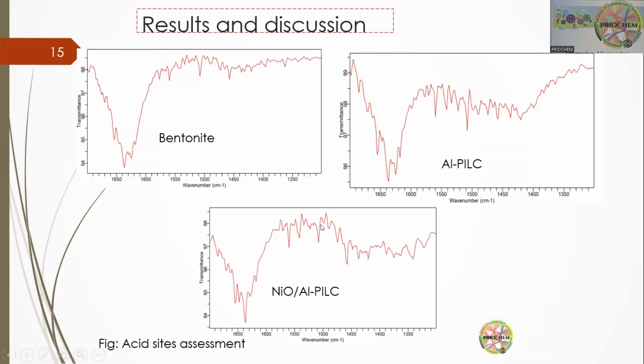Here is the pyridine adsorption in continuation with FTIR. The bands around 1440 and around 1595 correspond to the Lewis acidity, while the ones around 1500 correspond to the combination of Lewis acidity and Bronsted acidity. Here we did not quantify the acidity, but we did that to make sure we have seen the acidic sites, the Bronsted acid sites, and they are there in all the bentonite, the aluminum pillared clay, and the nickel oxide.